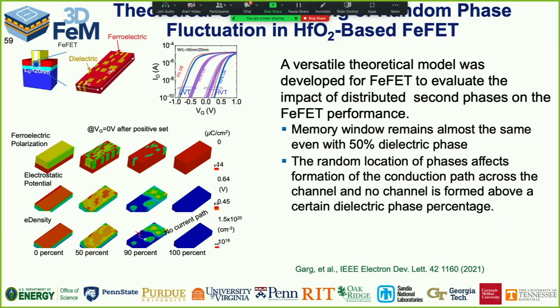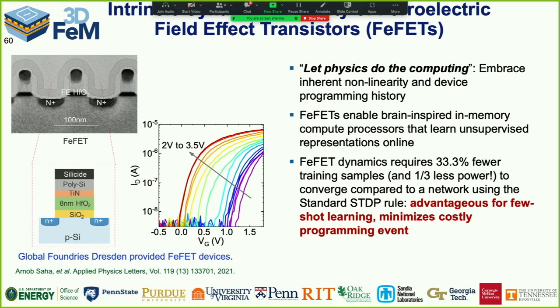The reality is they're always mixed phase. We always have some of the ferroelectric phase we care about and a parasitic phase that is not functionally ferroelectric. And that influences how well we can turn the channel on and off in a ferroelectric field effect transistor. This is a series of TCAD simulations that says as long as I've got at least 50% of the material which is ferroelectric, my memory window stays constant. So that's good.